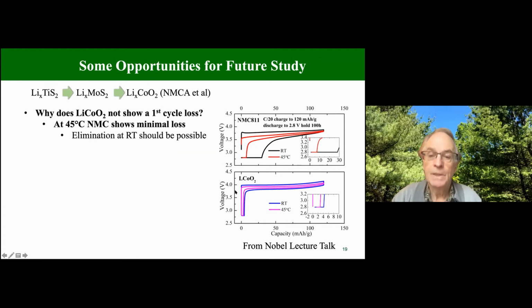If we do this for lithium cobalt oxide, charging to exactly the same amount of lithium, you can now see there's essentially no first cycle loss, and it makes no difference really whether room temperature or 45 degrees centigrade. So we believe by the appropriate modification of the NMC, we should be able to eliminate most of this first cycle loss. We haven't found the solution yet, but we believe it's out there.